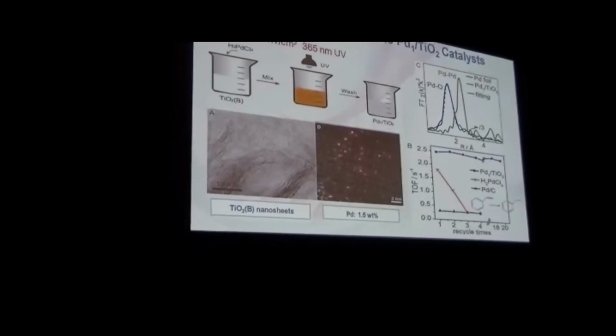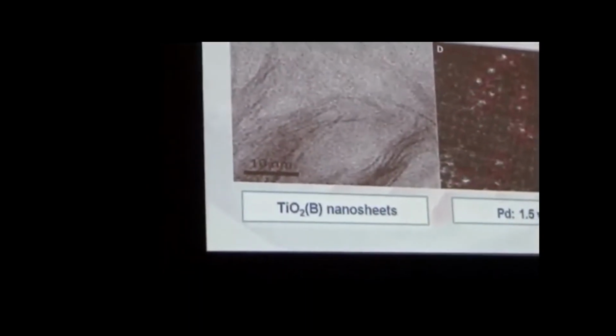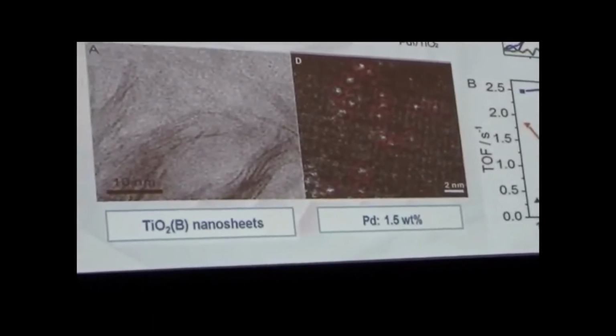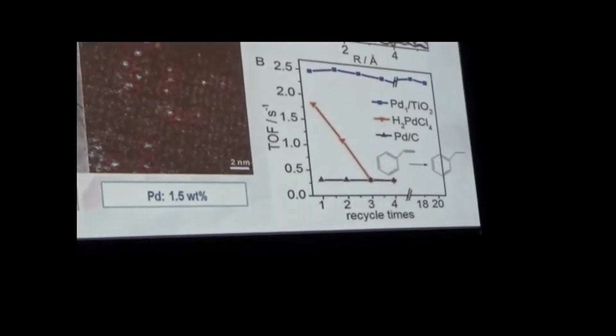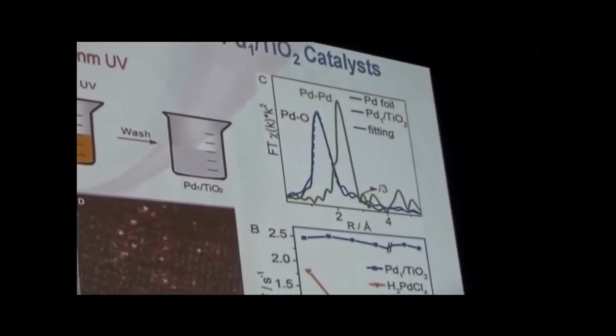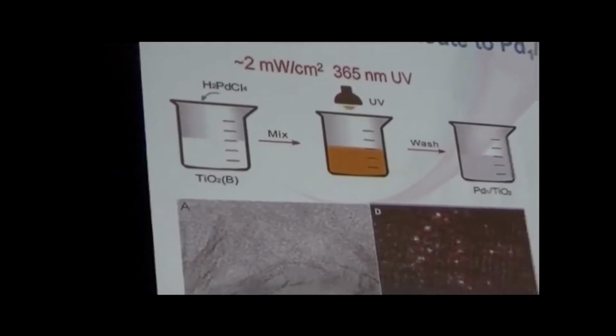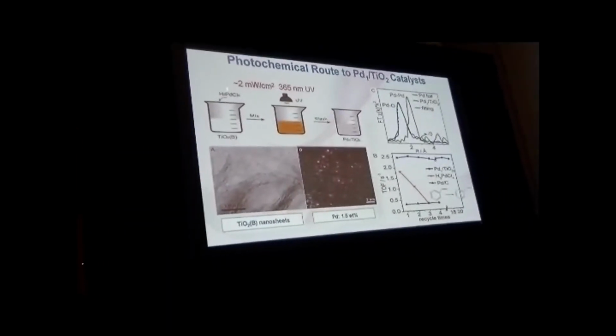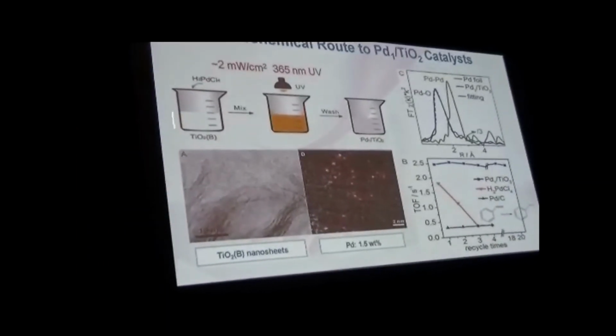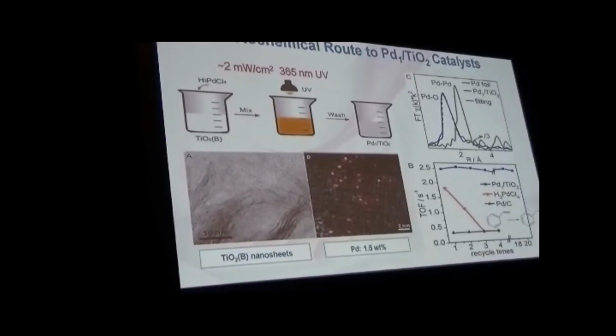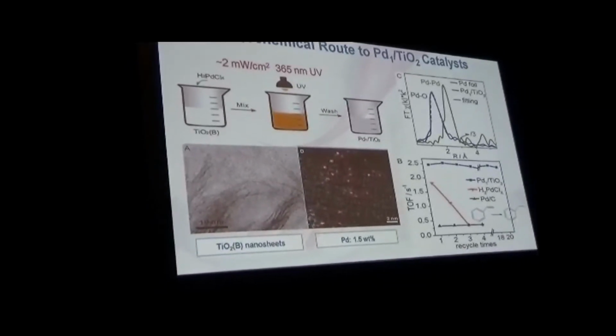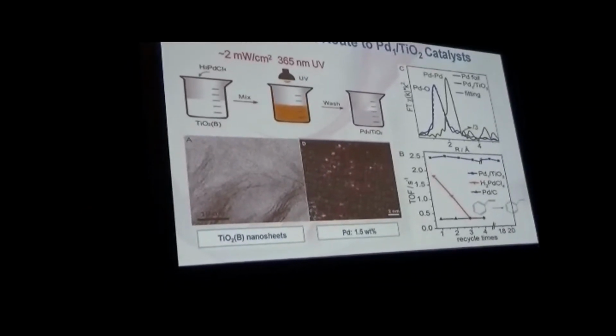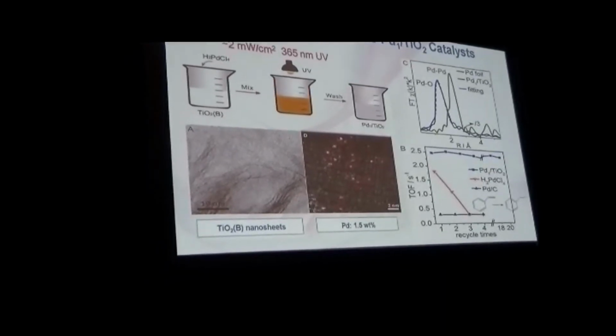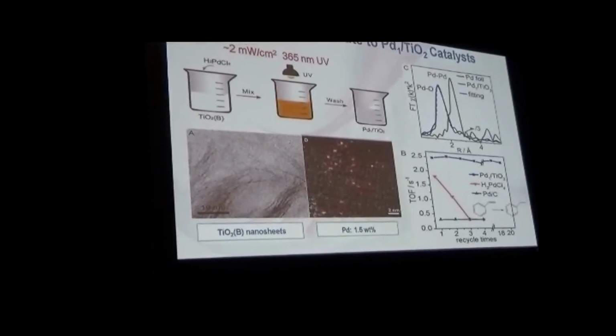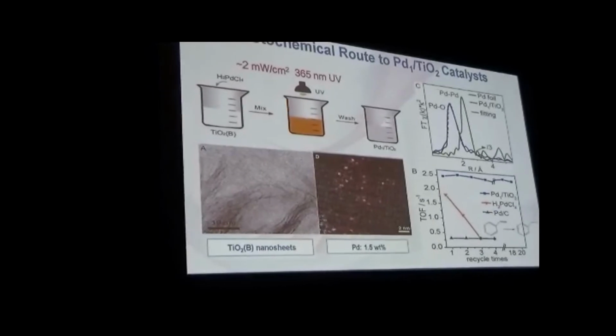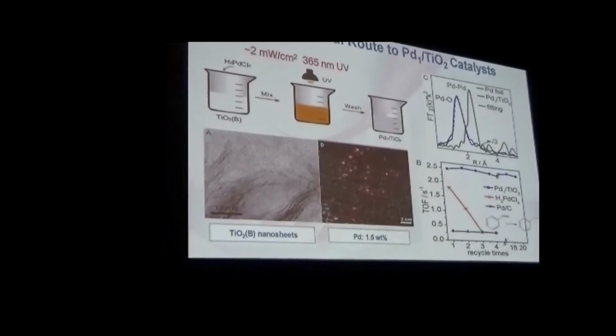So here we use a photochemistry route to prepare the Pd1 titanium oxide catalyst. In this case, we add chloropalladic acid to the titanium B. Upon UV irradiation, we can make the Pd1 titanium oxide, the atomically dispersed catalyst. It's a very simple way.